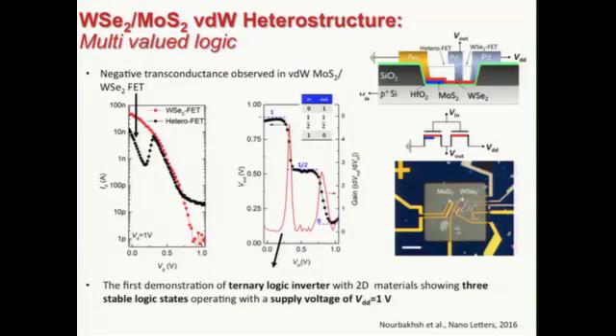But we also saw something very interesting in the transfer characteristics of the device. Actually, we see something similar. We have this peak with a peak to valley ratio of more than 10 in the transconductance. So it's a negative transconductance or sign-changing transconductance. Here you can compare it with a regular MoS2 transistor. The black one is the heterostructure.